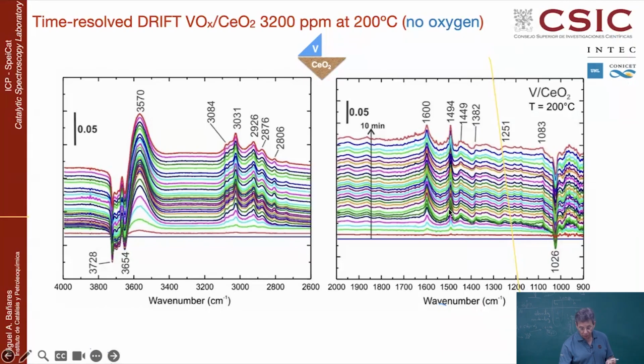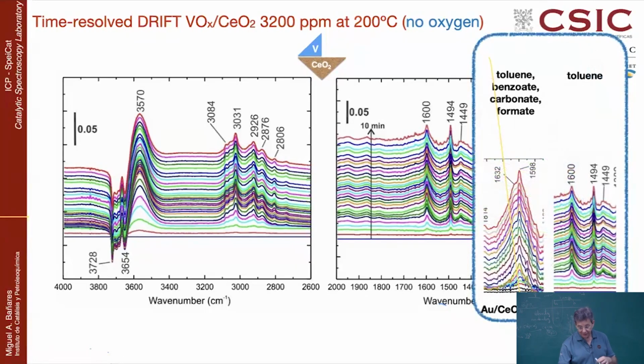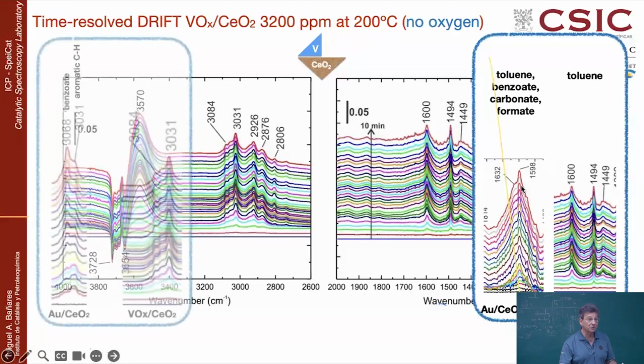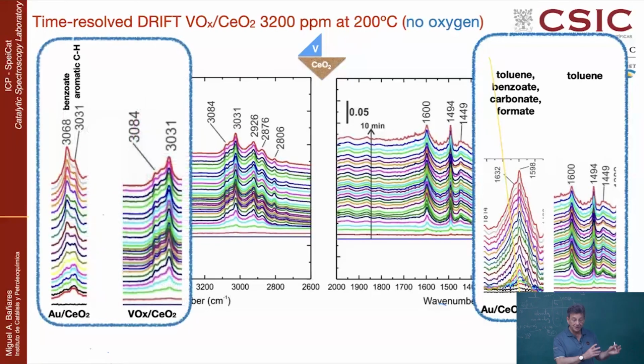And down here you absorb toluene, and what you observe is toluene, more and more and more toluene at the surface of this material. If you compare gold and vanadium, you absorb toluene on Vanadia ceria, and you get toluene, more toluene, but basically toluene. You absorb toluene on gold ceria, and you immediately get oxygenates, like benzoate, formate, carbonates, a big mess of things together, which is absolutely consistent with the CH region, where you see the evolution that is very, very limited for Vanadia ceria, where basically you get the aromatic CH and very little of the benzoate.